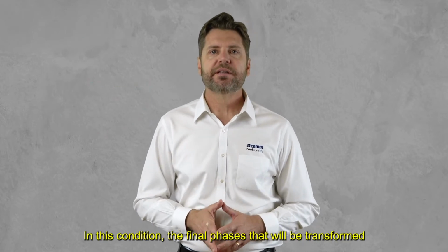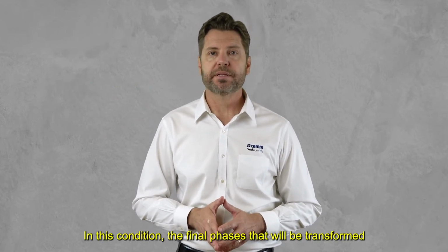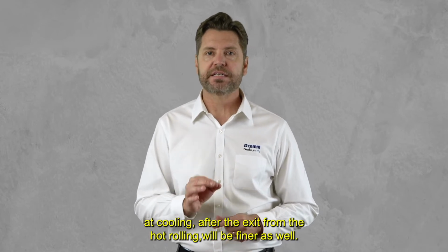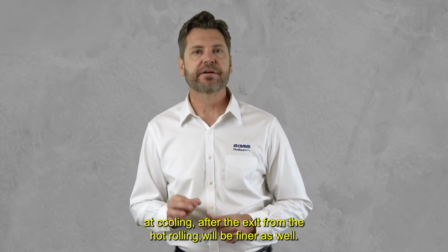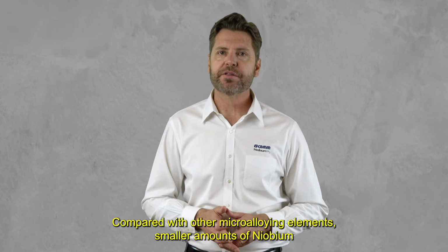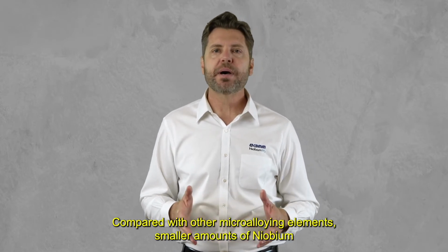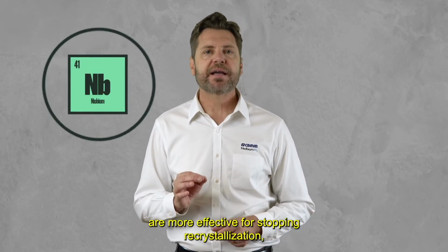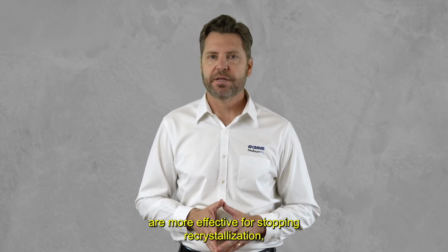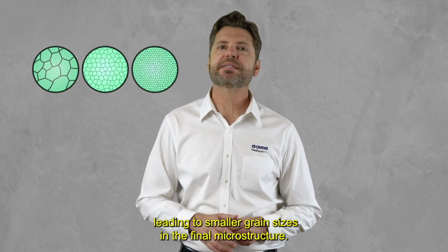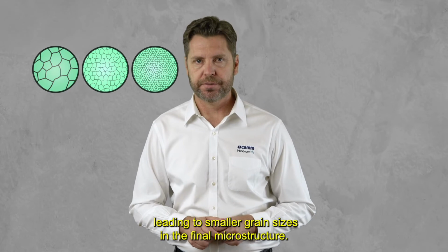In this condition, the final phases that will be transformed at cooling after the exit from the hot rolling will be finer as well. Compared with the other microalloying elements, smaller amounts of niobium are more effective for stopping recrystallization, leading to smaller grain sizes in the final microstructure.